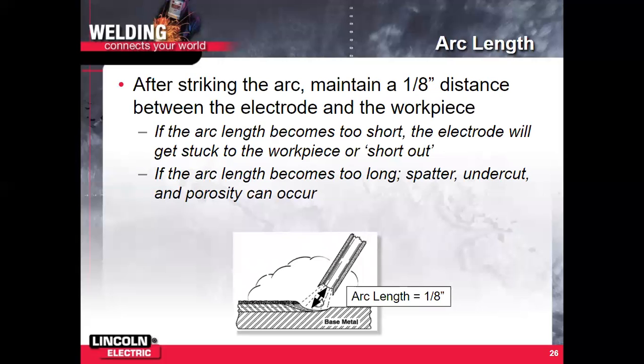So after striking the arc, maintain a 1/8 inch distance between the electrode and the workpiece. If the arc length becomes too short, the electrode will get stuck to the workpiece or short out. Basically, you're not allowing the space for the arc to clear. It doesn't get to establish. And if the arc length becomes too long, you get spatter, you get undercut, you get porosity.